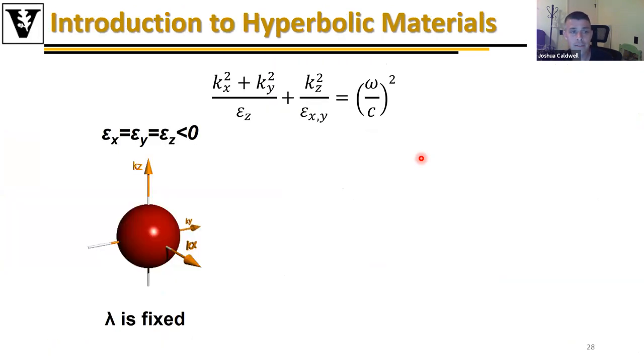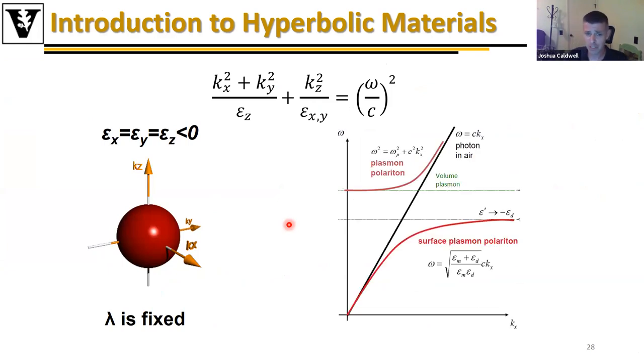Okay. So why is this important? Well, if I look at a traditional isotropic medium and I look at what's called an isofrequency contour, if I have all my permittivities negative and equivalent along all three axes, this means that my wavelength of the mode is going to be fixed. And you can see that from this dispersion here, right? This is just, again, the dispersion of a plasmon polariton. If I stick at an isofrequency, so a single frequency, I can find that the momentum of that mode is going to be fixed, right? And it's fixed by this dispersion. And therefore, that momentum, which is just the reciprocal of the polariton wavelength, is also going to be fixed. However, I can get that mode to propagate in any direction, right? So in any direction in space, it can propagate.